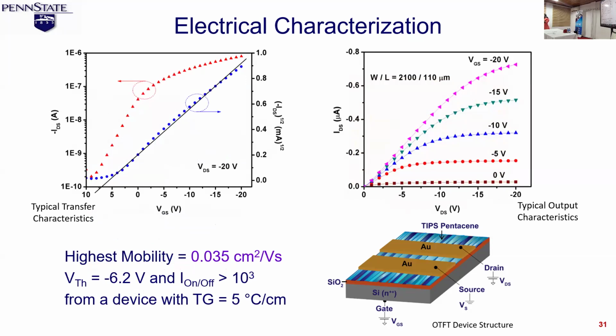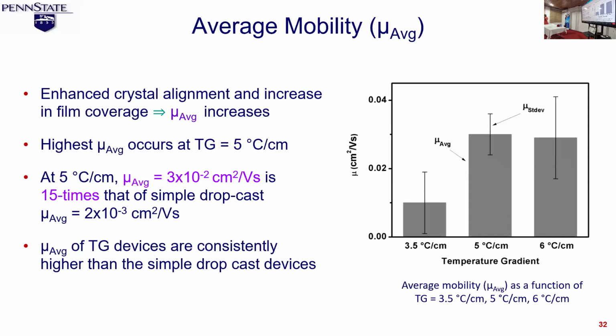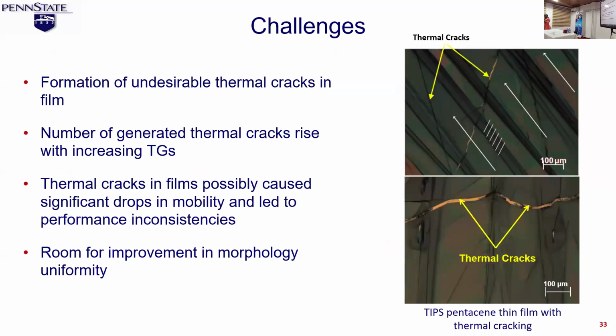All right, so the mobility for this is 0.035, which wasn't as high as I wanted it to be. So I had to investigate why this was not as high. But it was still better than the mobility without using the temperature gradient method. What I realized was that the reason the mobility wasn't as high as I expected was because there were cracks in the crystal that I didn't notice when I used the method. And the reason is that there was stress in the film. So obviously if there are cracks in the film, then you're not bridging the source and drain contacts the way we would want.